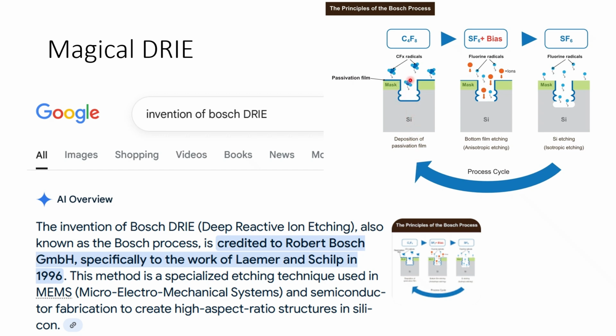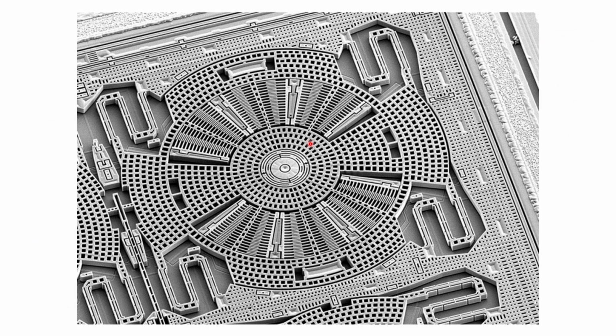The process involves plasma etching, followed by plasma deposition, and followed by plasma etching again. The etching is preferential on surfaces that are facing the plasma. So using this step, you can form very deep structures in silicon. The etching speed can be very high. And without this process, people would not be able to make highly sculptured structures like this in silicon. And such structures are very critical for inertial sensors such as accelerometers, gyroscopes, and so on.